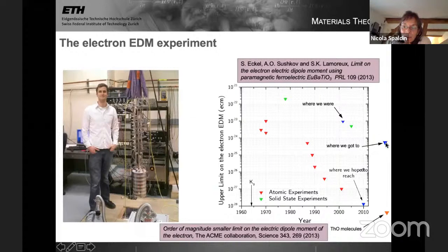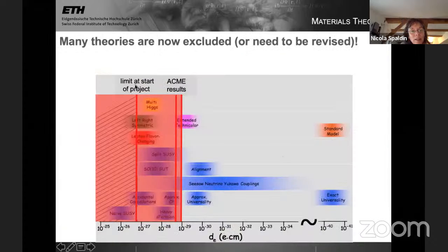And the reason for this was not that we didn't make what we had asked for, but that it was not possible because during the switching, the material heats up. And so it was not possible to precisely control the cryogenics, which was not something that we'd thought of ahead of time, but really reduced the accuracy. In the meantime, though, the ACME collaboration, in 2013, reached a value down here, and subsequently have even gone almost an order of magnitude smaller. And so, again, here's the plot. This was the limit at the start of the project, and the limit now is 10 to the minus 29 electron centimeters, which means that all of these theories are either excluded or have to be extensively revised.